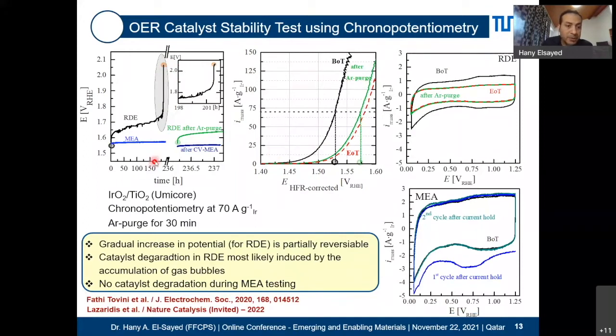Now, what I would like to show is that we applied these identical conditions in RDE to a membrane electrode assembly. And now what you can see is the following. The potential more or less starts at the same point. These are basically identical conditions. And what you see is the potential of the MEA is not even increasing at all, indicating that whatever phenomenon, which we believe is this microscopic oxygen accumulation, is happening in RDE to a significant extent, it is most likely also happening in MEA, but to a much, much lesser extent. That's why the MEA potential does not really increase.